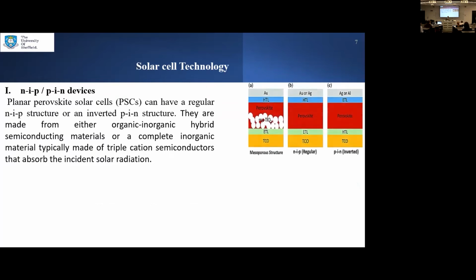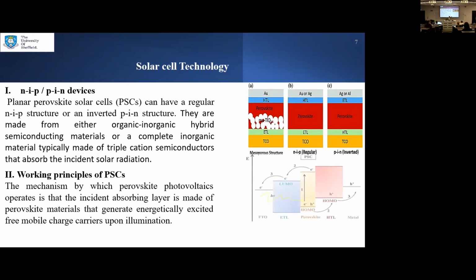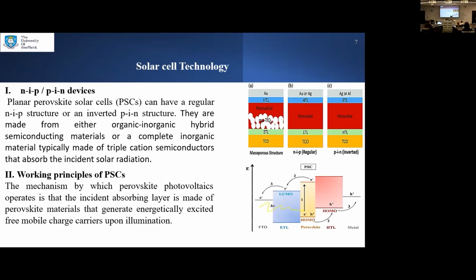So, the perovskite architecture. Actually, perovskite solar cells are being made either using an inverted method or a regular method, or using a mesoporous substrate. And the way it actually works, you have the perovskite absorbing layer, and it tries to create electrons and holes, where they try to separate using an electron separation layer, and then a hole separating layer.